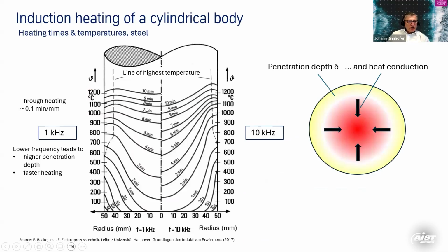What does that mean? For example, 1 kilohertz frequency gives you a much lower heating time in comparison to 10 kilohertz, so it's very quick. It's quicker at 1 kilohertz because the penetration depth is a little bit higher. You see that in 10 minutes you can completely through-heat a billet of 100 millimeter diameter. That is 0.1 minute per millimeter, recall the 1 minute per millimeter in a fuel-fired furnace. So it's really, really quick.